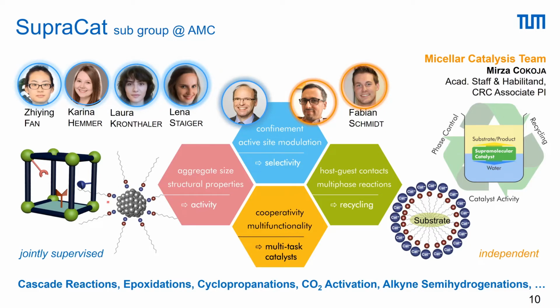So in our case, we put the surfactant-stabilized metal nanoparticles inside the MOF material, or we just work with the nanoparticles in colloidal solution themselves. So confinement and active site modulation play a role. Of course, then the aggregate size plays a role, and host-guest contacts and multiphase reactions play a role. Here we have the solid-liquid interface. Here you have more or less this soft colloidal micellar liquid interface.